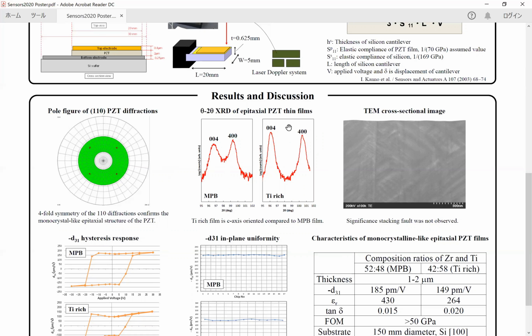The C-axis orientation ratio of the titanium-rich film is higher than that of MPB film, which was calculated from the comparison of intensities between 400 and 004 peaks of PZT. These results indicate that the permittivity of titanium-rich film is lower than that of MPB film because C-axis oriented PZT-based epitaxial thin film has small dielectric constant. This is a TEM cross-sectional image where significant stacking fault was not observed.